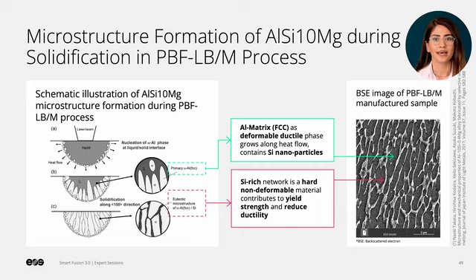Alpha aluminum phase has an FCC crystal structure, which is known as a deformable ductile phase. Previous studies have also shown the existence of silicon nanoparticles within alpha phases. At the end of the solidification phase, a silicon-rich network forms at the boundaries of alpha phases, showing that this alloy has a eutectic microstructure. The silicon-rich phase acts as a hard, non-deformable phase, and its presence leads to lower ductility and higher strength and hardness in the material.